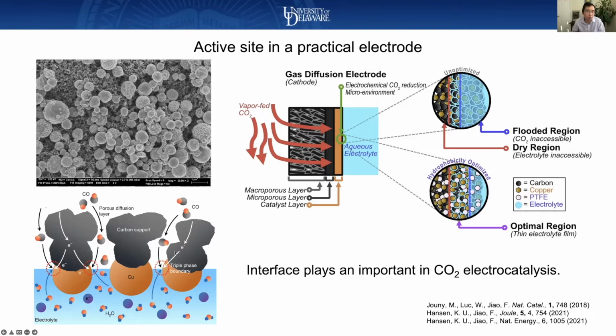So if you really zoom in, what's going on here is actually another layer. You have carbon particles, which not only conduct electrons, but also provide some level of hydrophobicity. And then the liquid electrolyte is trying to wet the surface and conduct charges to the interface. So the real system is very complicated. We got involved in trying to develop new tools which allow us to have a complete picture of what's going on at the interface. And there are several things.